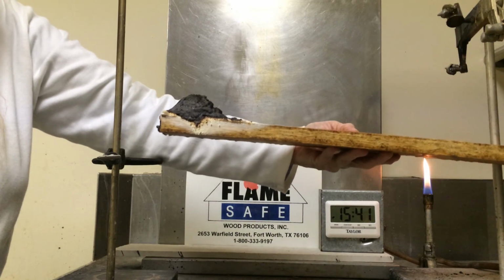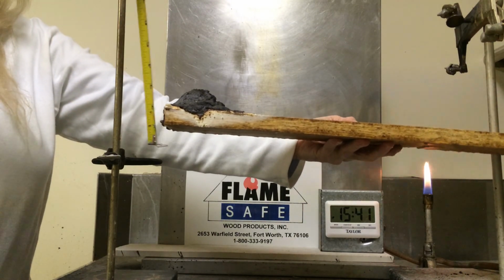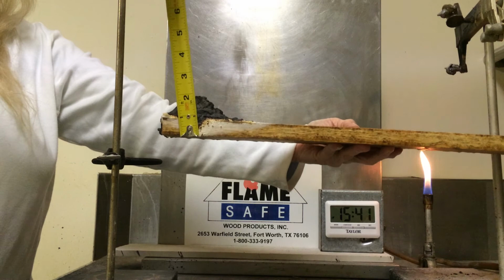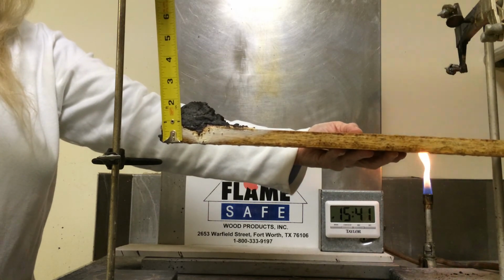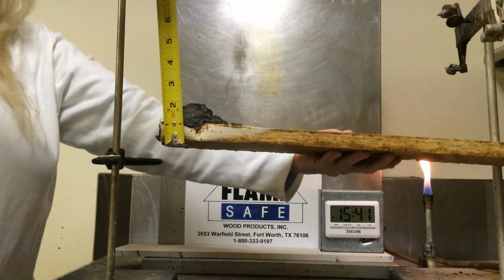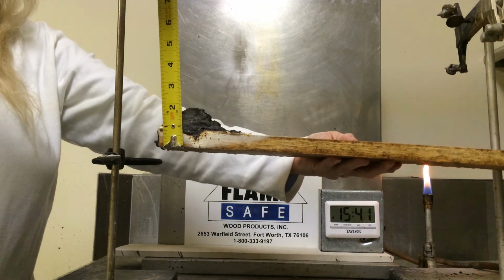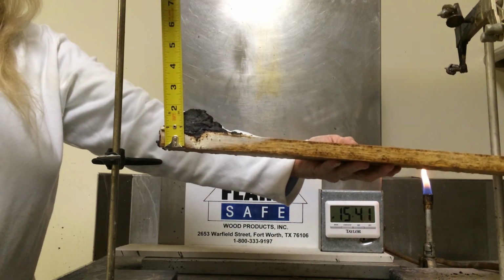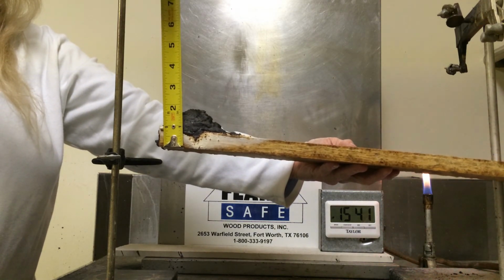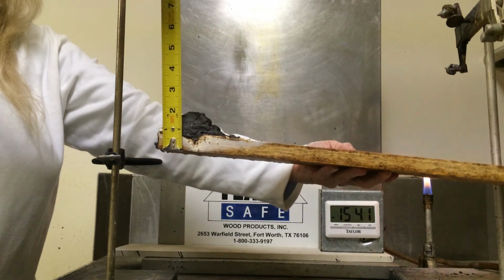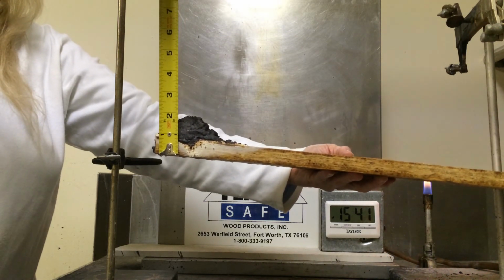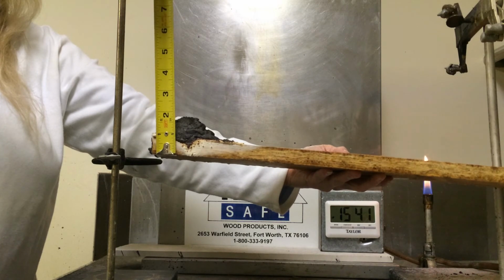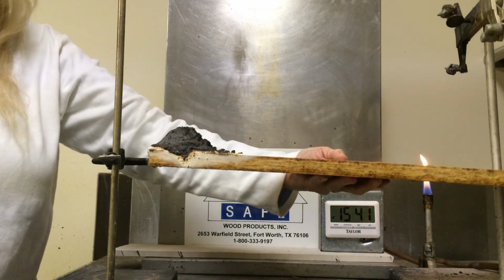If you'll notice the expansion on the 3/4 inch specimen, it is now 2 3/8 of an inch in height, approximately 1.5 inch expansion of the intumescent coating.